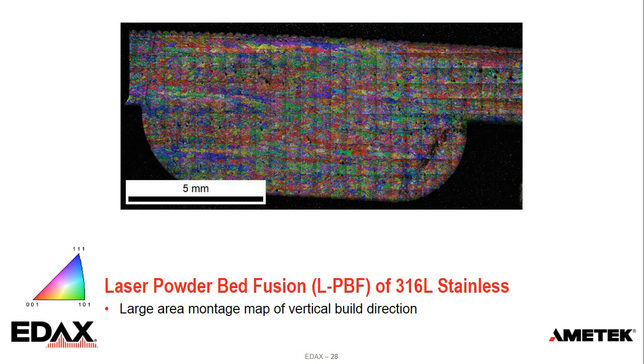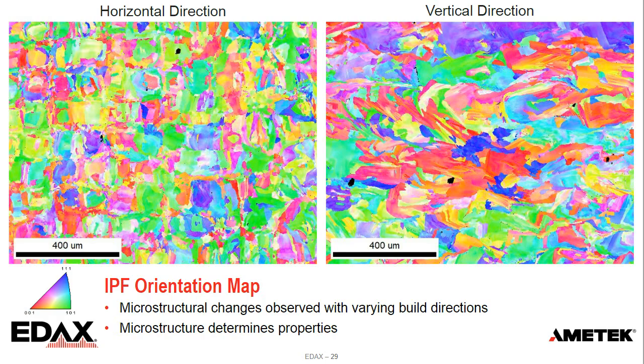Looking at these at a little higher magnification, you can see that the microstructure is very different between the horizontal and vertical directions. This is essentially part of how the energy beam interacts with the particles, the solidification and heat transfer rates, and then how it goes from one layer to the other, the direction of the rasters, and there's a lot of things going on in there. And again, if you're able to adjust your build parameters to adjust your microstructure, and microstructure determines properties, being able to measure your microstructure is a key component in really moving forward with this.